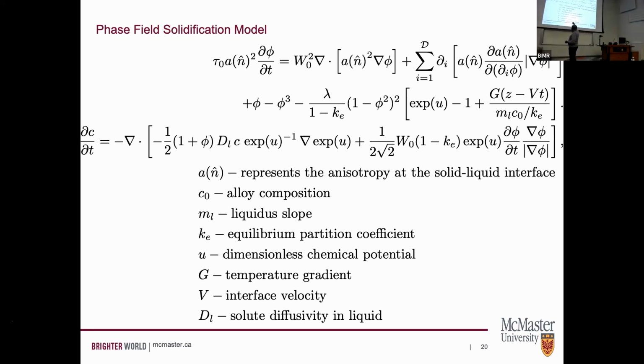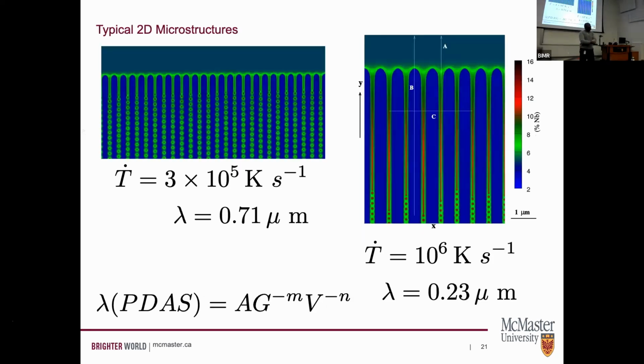The order parameter equation, i.e. the state, tells me things about surfaces and anisotropy. That's the first line. The second line here tells me about the driving force. In this case, the things I've extracted from my finite element calculations are things like the temperature gradient G, and the velocity V, and the M, C0, and K are all material parameters that are associated with the alloy I'm interested in and where in that phase space I am. The rest of the parameters you don't need to concern yourself with at this point.